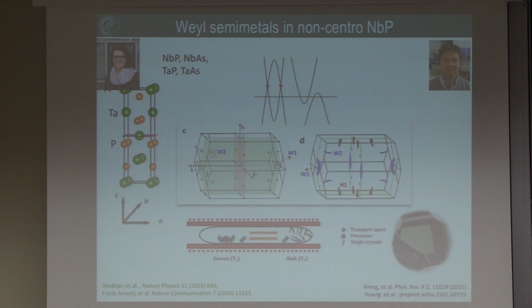When Andre's group predicted, together with the IOP, this class of materials, we could quickly grow them. They are also not so difficult to grow—you first make the powder, then you transport them, and you get very nice single crystals.